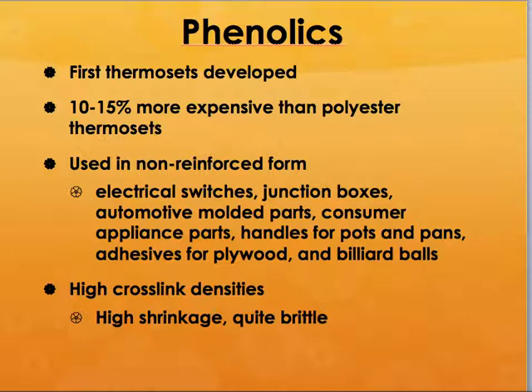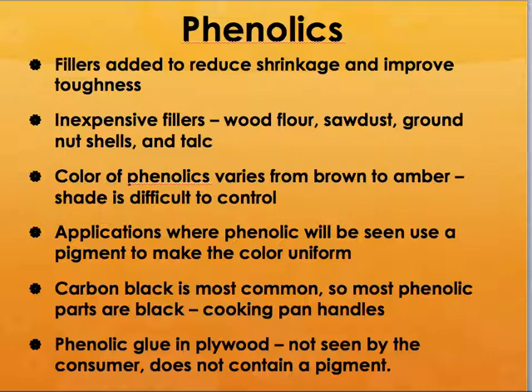So when you want to make a carbon-carbon composite from a phenolic type of resin system, you have to do infusion multiple times in order to get the highest densification possible for these composite systems. In order to avoid that, you add fillers that can be used to reduce the shrinkage and improve the toughness. Some of the fillers that you use are wood flour, sawdust, talc, etc. By doing that, you can reduce the amount of shrinkage, but still you cannot completely avoid the shrinkage, which is something to note here. The color of phenolics can vary from brown to amber, and that shade of the color is extremely difficult to control.